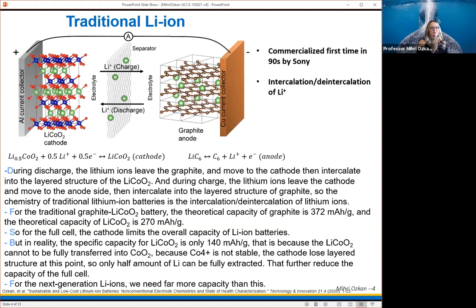If you look at it from the performance perspective, the theoretical capacity of graphite is 372 milliamp hours per gram, and for lithium cobalt oxide, it's 270 milliamp hours per gram. In this scenario, we see that it is limited by the cathode. So the cathode is the limiting factor for the performance of the batteries. Even though the theoretical capacity is 270, today with lithium cobalt oxide cathodes, we only achieve around 140 milliamp hour per gram in real applications because of instability issues and also simply losing the layered structure of the lithium cobalt oxide during charging and discharging.